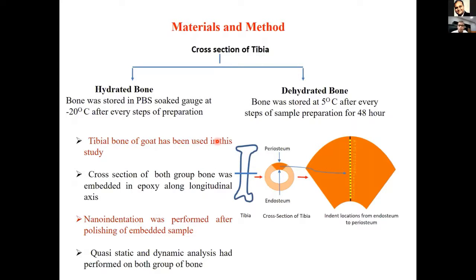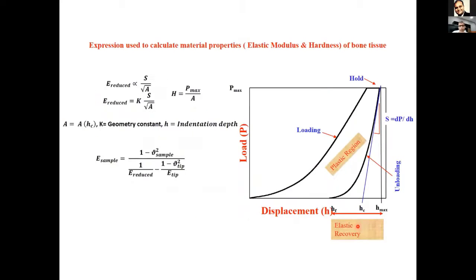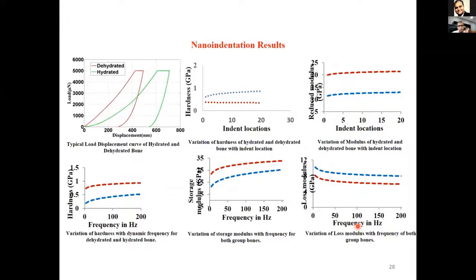And here what we have done is we have done this indentation at different locations from the endosteum to the periosteum locations, and nearly 20 indents we have done, in quasi-static and dynamic loading conditions. So the same formulation we have adopted here. So here you can see that the dehydrated is the red one. Sorry, the dehydrated is the red one, and the hydrated is the green one.